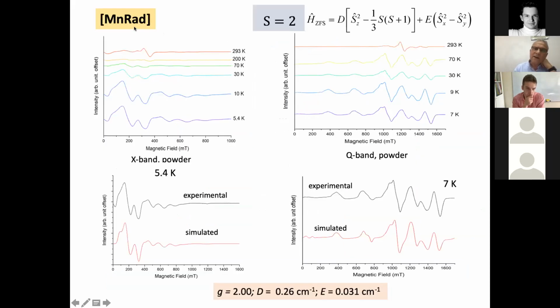The case of manganese is even more interesting because we can observe below 120 Kelvin nice spectra of S = 2. This is in X band powder, the other one in Q band, and the simulation of the spectra is, in both cases, in line with the experimental lines which are observed.